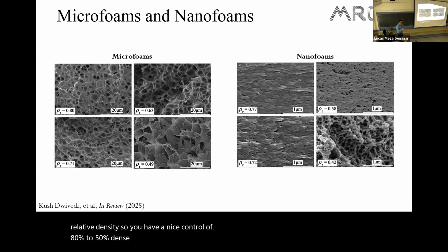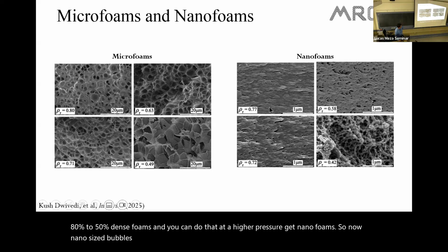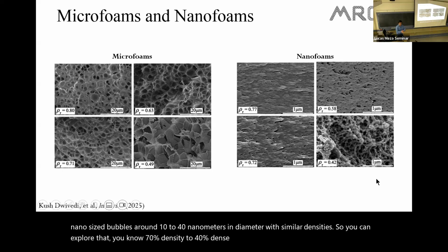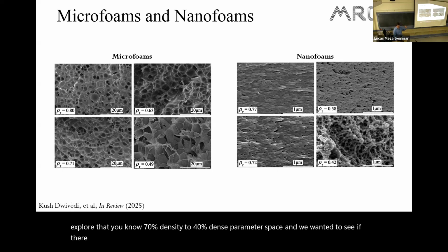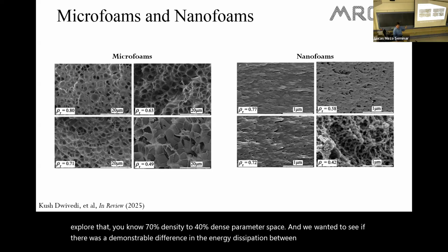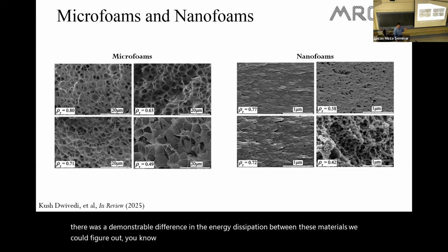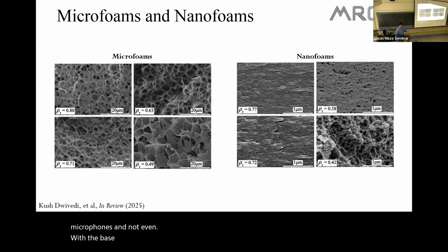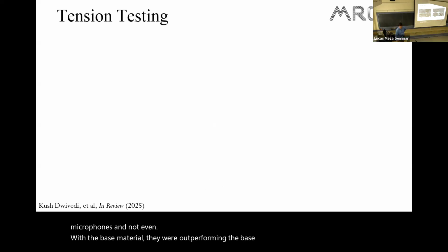And you can do that at a higher pressure and get nanofoams, so now nano-sized bubbles around 10 to 40 nanometers in diameter with similar densities. So you can explore that 70% dense to 40% dense parameter space. And we wanted to see if there was a demonstrable difference in the energy dissipation between these materials, so we could figure out why we were seeing these odd results with nanofoams and not with microfoams, and not even necessarily with the base material. They were outperforming the base material in some cases.